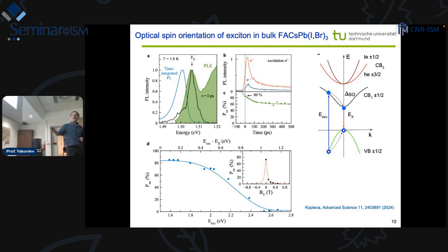But why does this decay happen then? There can be two reasons for that. One reason is that some spin relaxation really starts for these high-lying states. Another reason is that when we excite so high, our band states are not so pure. So we have this 100% polarization for generation of the spin only for the states closer here.